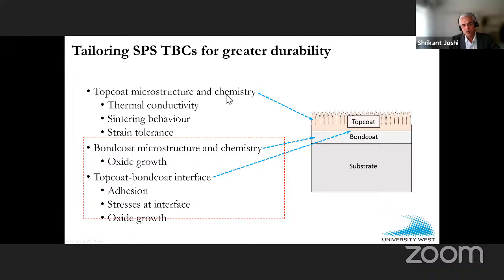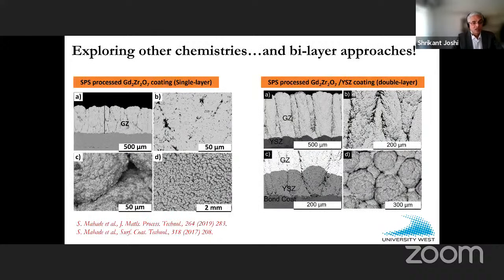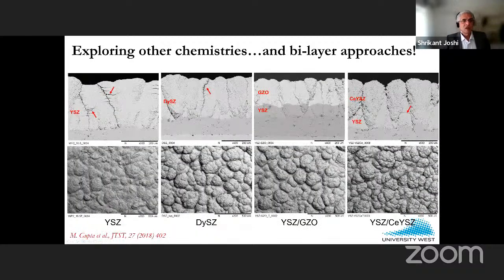We have been looking a lot at chemistry, moving away from yttria stabilized zirconia, for example. We have been looking at microstructure, column density, and things like that. We have been looking at architecture, single layer ceramic TBCs and multi-layer ceramic TBCs. And yeah, it's been a long but very educative ride. Some examples from our group again. I spoke about multi-layer TBCs, trying to combine yttria stabilized zirconia and gad zirconate. Also looking at some other chemistries of interest in an effort to reduce thermal conductivity and enhance coating lifetime.